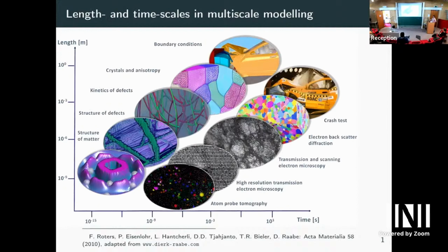If you want to go even further, at some point you still have to model billions of atoms, and they attain all sorts of structures. Sometimes you're only interested in the structure itself, as opposed to what every atom is doing. Then you can coarse grain again, and for instance, we see the jump from here to here. These lines are dislocation lines, and this simulation is called discrete dislocation dynamics. You basically just trace the fronts of these crystalline defects, and somehow you disregard the information about atoms.